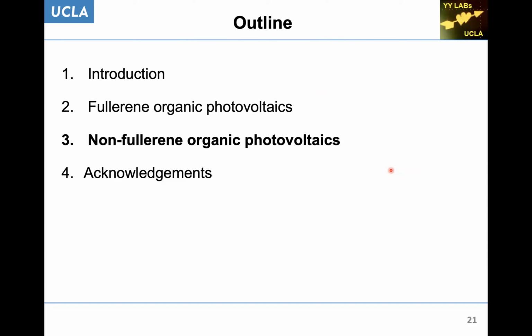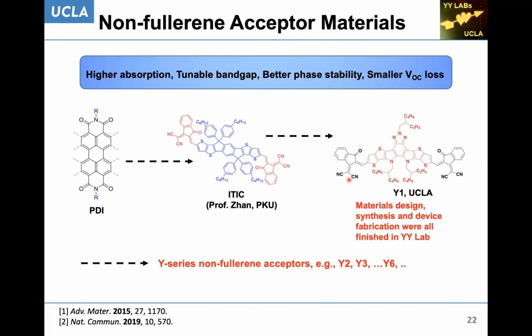So now we enter the so-called non-fullerene organic photovoltaic. This is the non-fullerene material, using a 1986 paper by Professor Ching Tang. He was a scientist at Kodak at the time. And then Professor Zhan Xiaowei at Peking University was the first to make ITIC, a non-fullerene acceptor. And then we worked on the Y1 molecule in my group, and we published a paper in Nature Communications on the Y1 molecule. And subsequently we made Y2, Y3, and our collaborator in China, Huazhong University of Science and Technology, actually reported the Y6 molecule, which has become more or less a standard molecule in the organic photovoltaic field.